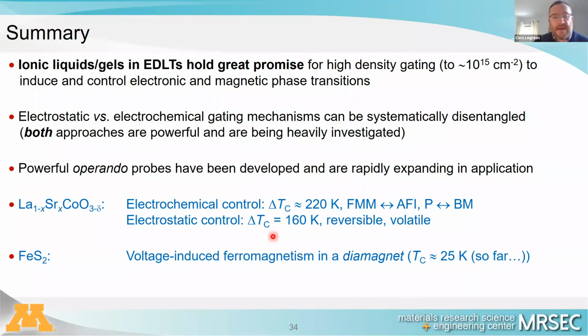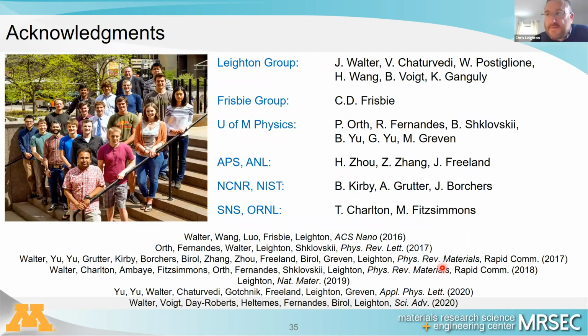Using electrostatic control, we can do not quite as well, but we can still modulate the Curie temperature over about 160 Kelvin. And then in our work trying to induce ferromagnetism in a diamagnet, we've shown that this is in principle possible. We've gotten to a TC of only 25 Kelvin, but I think there's a lot of potential to go higher than that, even just in the pyrite system. We haven't looked at any others.